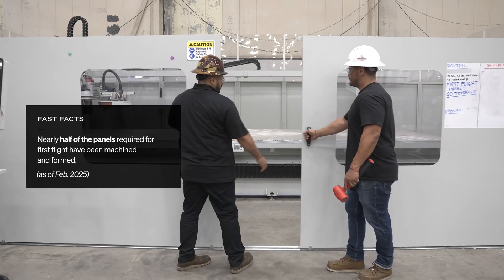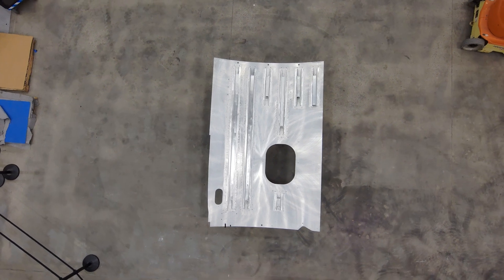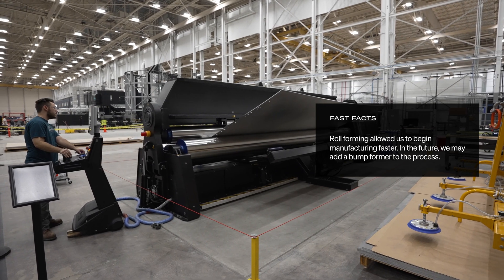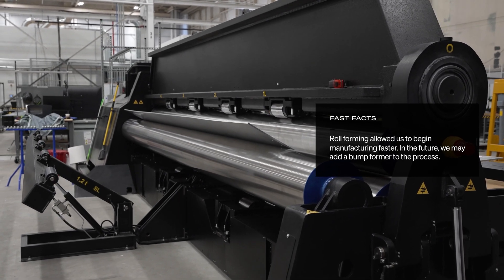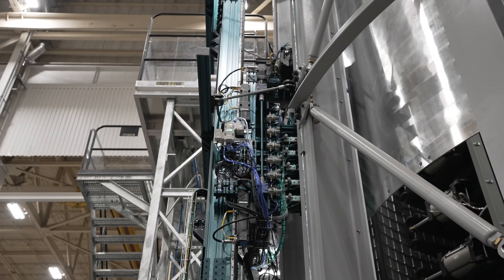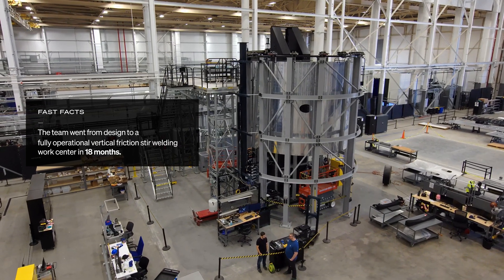The entire process starts with raw material arriving on the dock. We then mill out the panels ourselves, removing mass where we can to both optimize for strength and optimize for mass. We go through a rolling process where we take these panels and bring them as close to cylindrical geometry as we can. It doesn't have to be perfect because the friction stir welders we've designed have the ability through tooling and different clamping methods to bring approximately cylindrical barrel sections into the correct tolerances to proceed through the friction stir welding operation.